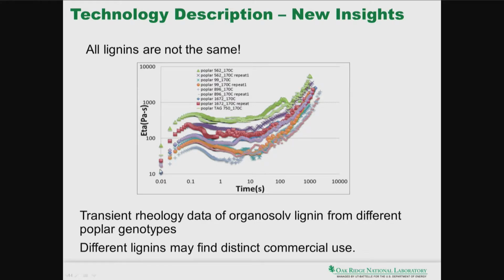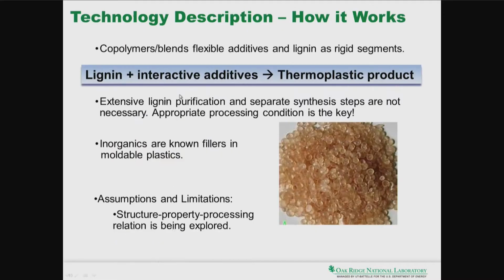And if we do softwood lignin, in fact, you will see that those will not flow, and the viscosity will go at least 4 or 5 orders of magnitude higher, and that would stop the rheometer. So that is how different kinds of lignin would work to make different kinds of thermoplastic. Of course, we have to add some other additive, and those additives can be functional additives. There can be a covalent bonding between those additives and the lignin, or there can be just physical interaction, and we can make the thermoplastic product.